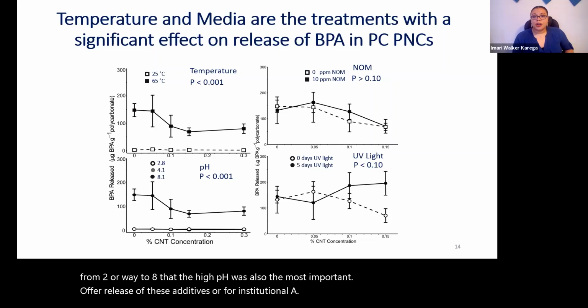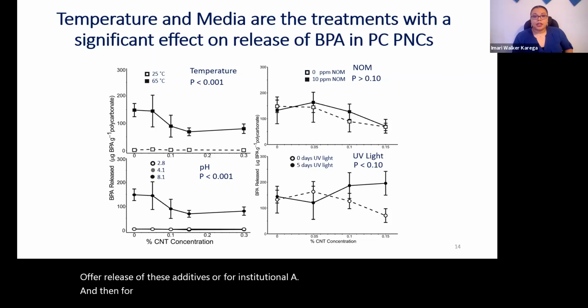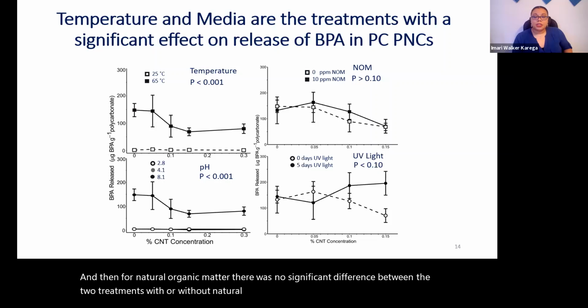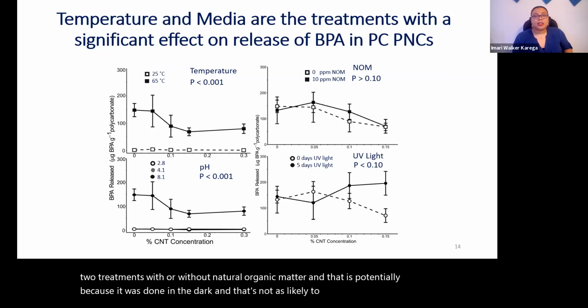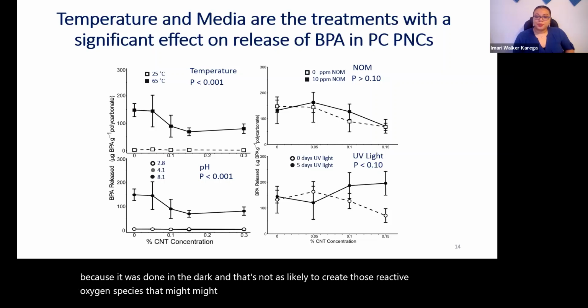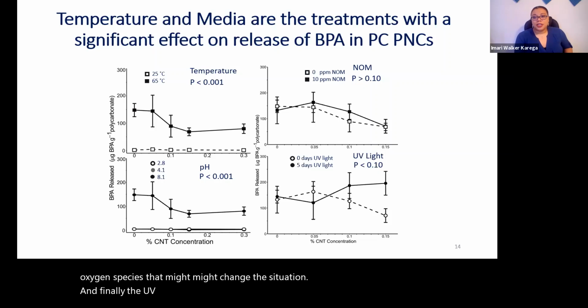For natural organic matter, there was no significant difference between the two treatments with or without natural organic matter, potentially because it was done in the dark, which is not as likely to create those reactive oxygen species that might change the situation. And finally, for UV light, there seemed to be no significant differences between the two treatments, except when you